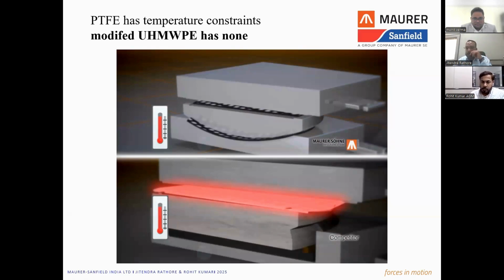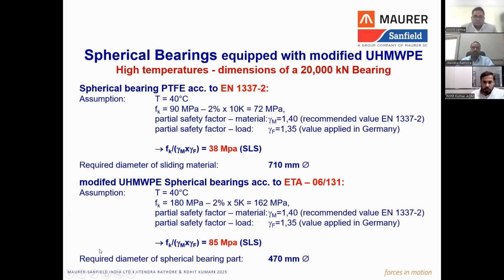Whereas in case of approved UHMWPE, it is able to tolerate a temperature exposure up to 110 degrees centigrade also. This is mentioned in the approval documents that if the material is of proper grade, proper construction, the compound is correct, it can go up to a temperature exposure of 110 degrees also. Coming on to the design part, the advantages that we get by using these innovative sliding materials is a compact bearing shape and form.